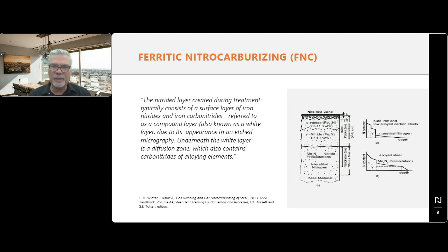The small letters that you see, epsilon and gamma prime, show two different phases of the white layer or the compound layer. Just below, you see another small diagram which shows hardness with metallic and nitrides precipitated in the case, and this contributes to the core hardness, to the case hardness. So you don't only have a white layer, but you also have a very hard diffusion case.